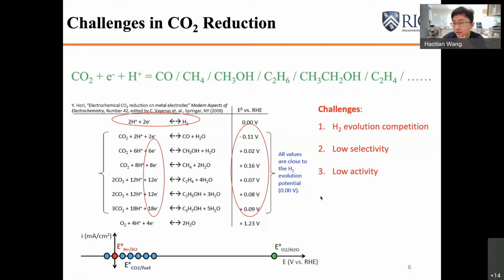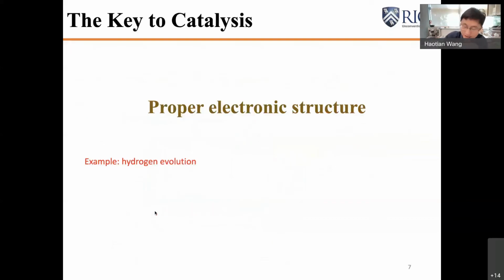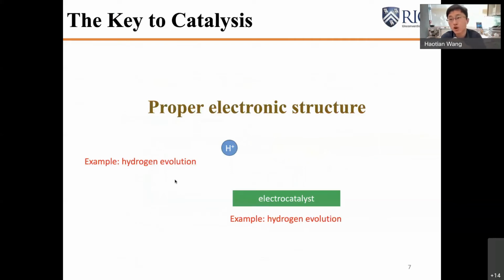And the low activity means that if you look at high value products like C2 or even C3 products, there are more than 10 electron transfer steps. So if there is only one electron transfer step that has a very high kinetic barrier, the overall reaction speed will be slowed down. So how to address those challenges actually relies on better control of the catalytic material's electronic property.